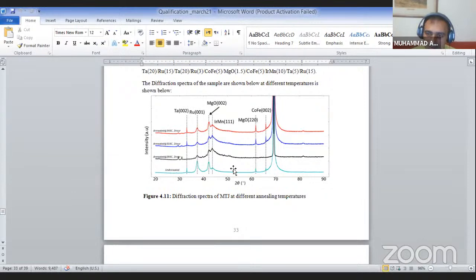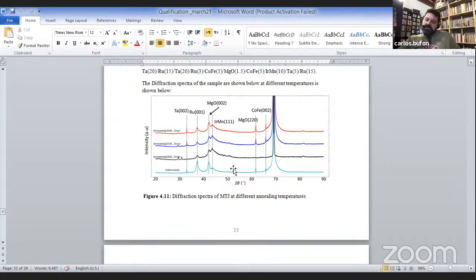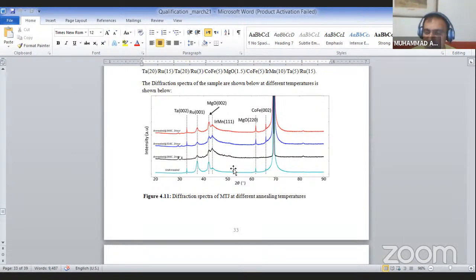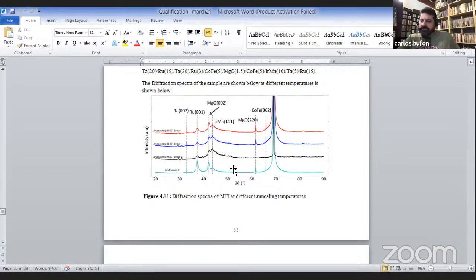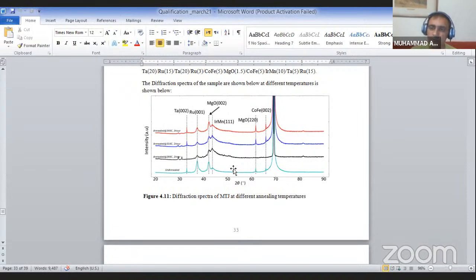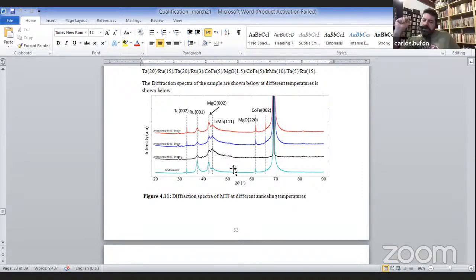But which kind of oxide do you have? A polycrystalline or amorphous oxide? It doesn't matter, because aluminum oxide can be amorphous. It is amorphous. Okay, because it means you exclude completely the formation of grain boundaries. Yes, Professor. Because we can crystallize aluminum oxide in an annealing process as well.